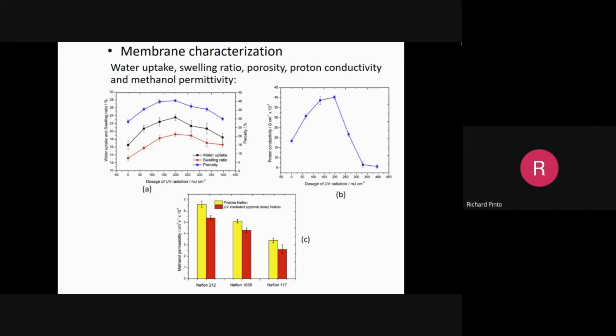Membrane characterization is shown here. Water uptake, swelling ratio, porosity, proton conductivity, and methanol permeability are all shown here. All four are very important characteristics. Water uptake is required for maintaining conductivity. Swelling ratio is also important. Porosity is also important for proton conductivity, which should be maintained at a certain level. And proton conductivity is shown on the right side. These are important properties of the membrane. This is the electrical property, the proton conductivity of the membrane itself.